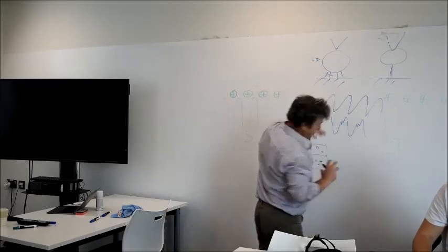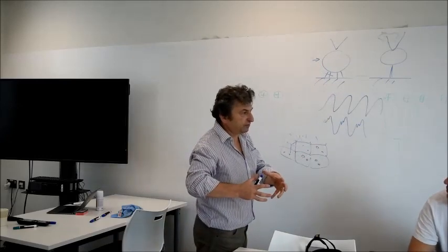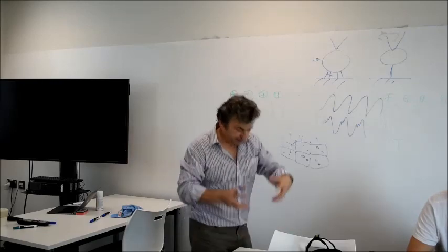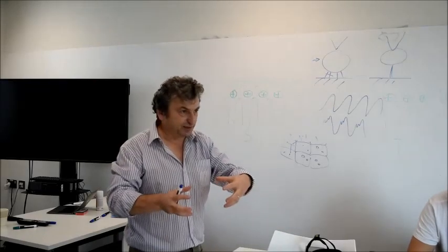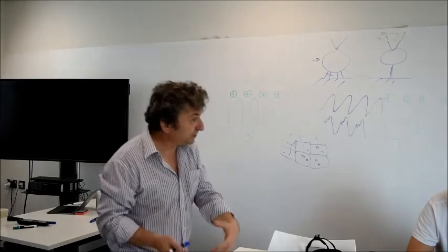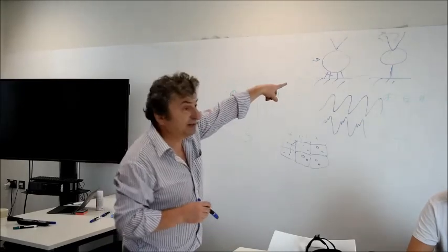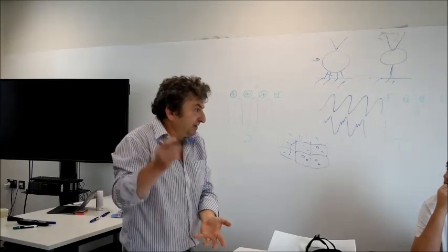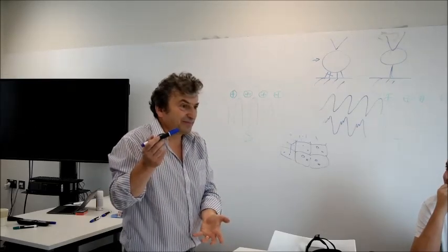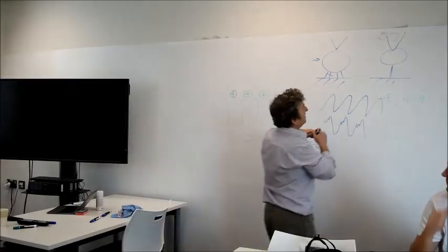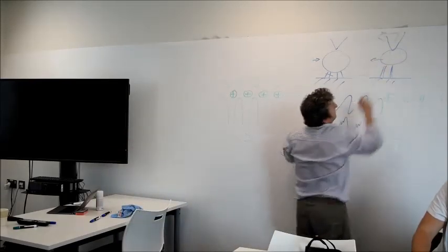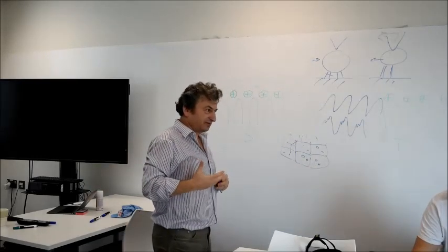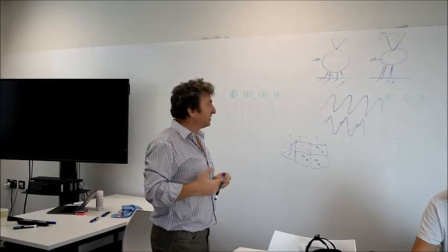So, by pivoting the molecule halfway through and then lifting, that works, yes? So, we can pick up the molecule and then move the tip to another position and drop it. But again, if you drop it on the surface like this, it will be in that position. So, you want to remove the tip and keep the molecule on the surface, but the tip will take the molecule with it, right? You have to roll it back. You roll it again, yeah. You roll it back with the tip until you have four bonds, and then you remove the tip. So, that's a mechanism of vertical manipulation of the molecule, yeah?